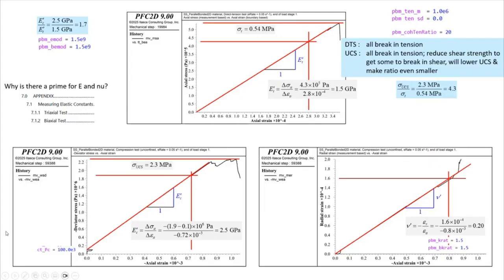Then we went here. This was the UCS test that was run. So again, I could pull it up and this is what we just looked at. This is the stress strain curve. I made a snap. I took a line. There we go. This now is the compressive modulus. Again, it's a 2D thing, so I'm going to put the prime there. Stress over strain. Here we go, 2.5 GPa. Here's the UCS value. 2.3 e to the 6th pascals. That's megapascals, right?